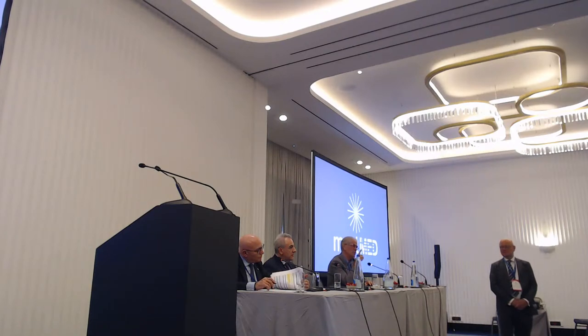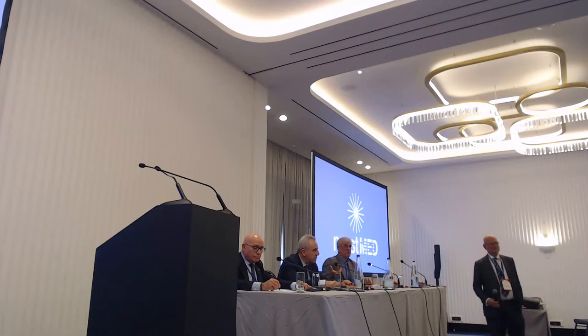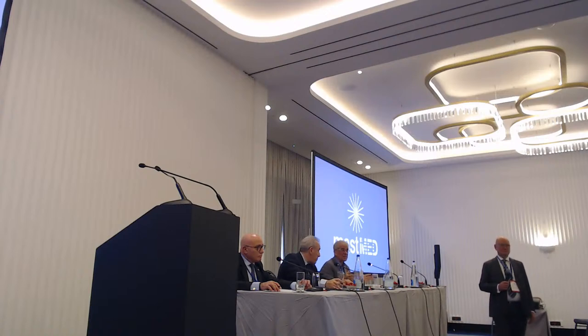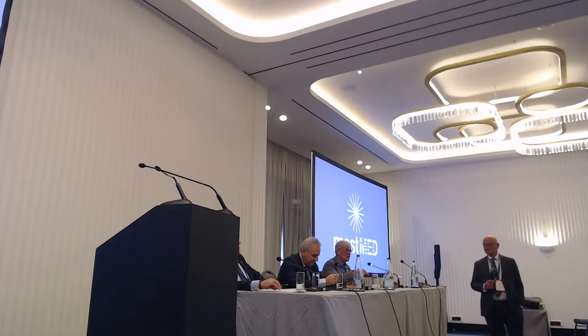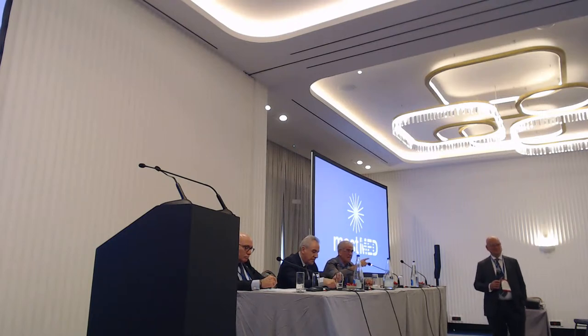If you want an answer from 0 to 10, I'm not the right guy to give such an answer, but I would say 7. By means of not losing something by the neutron diffraction in depth, and by not losing information for surface stress measurement. However, the 7 and not 9 or 9.5 comes because the neutron diffraction is rather averaging in the whole thickness, whereas other techniques can provide stress depth distribution also, which is one of our targets together with superior technologies in this field.